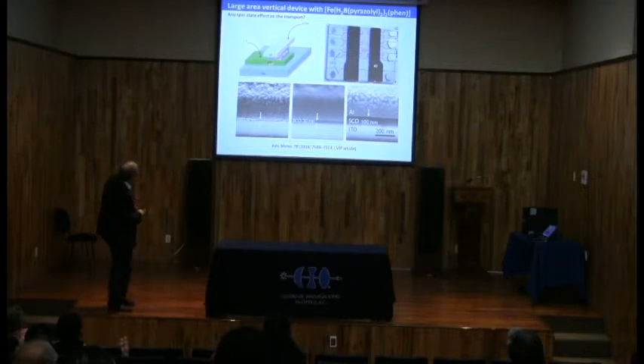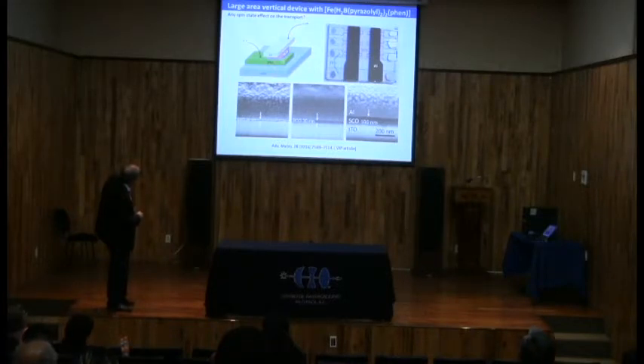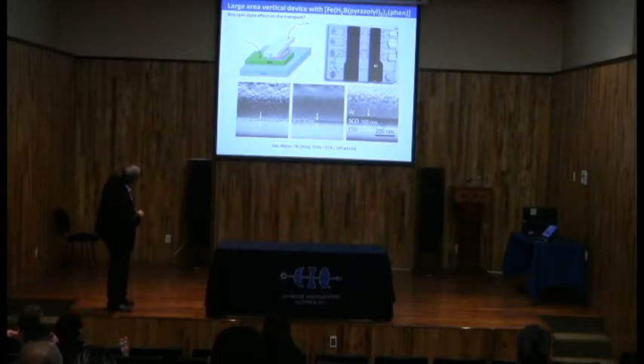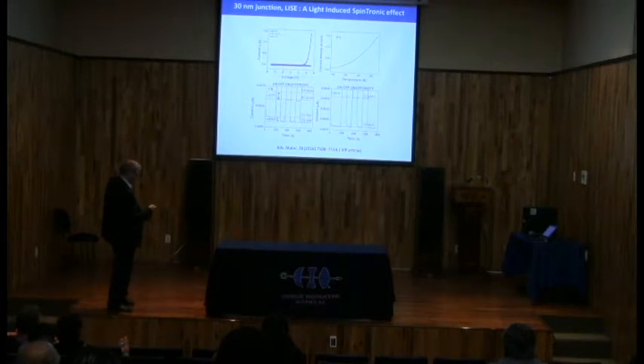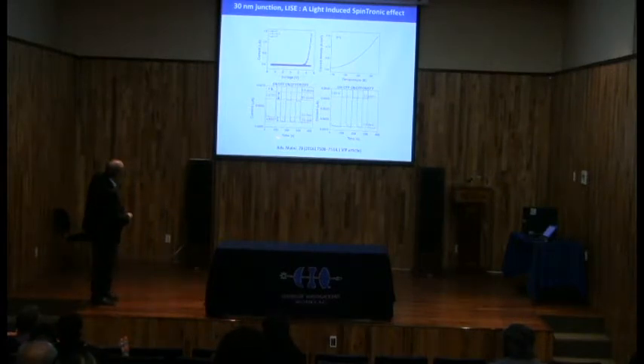Here, what you can see, we have our spin crossover film, and then we have aluminum here and ITO, and we try to see the properties of the spin crossover film, and then the transport through this junction. If we take this 30 nanometer junction here, you see that very quickly, for example, in this experiment here,